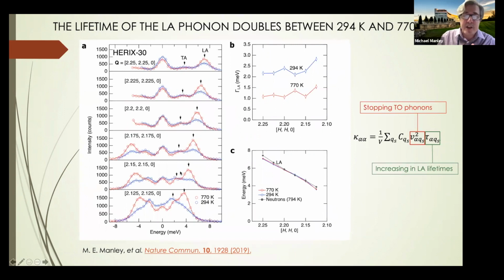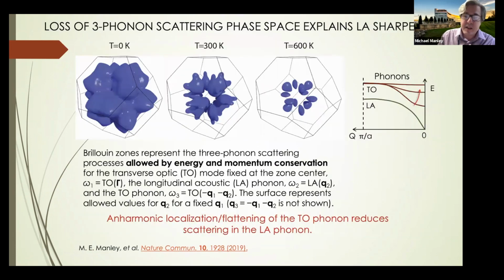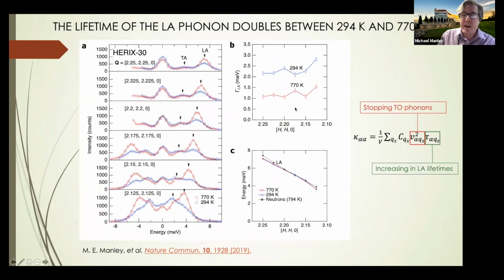So we repeated this measurement because we were kind of surprised. Phonons are not supposed to become sharper with increasing temperature, because as you increase the temperature, there are more other phonons for it to scatter from. But sure enough, we repeated it with X-rays, and we got the same result. It didn't matter. The numbers were the same. The lifetime of the phonon was basically double at 770K as it was at room temperature,